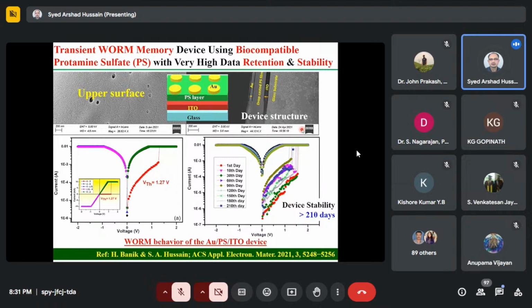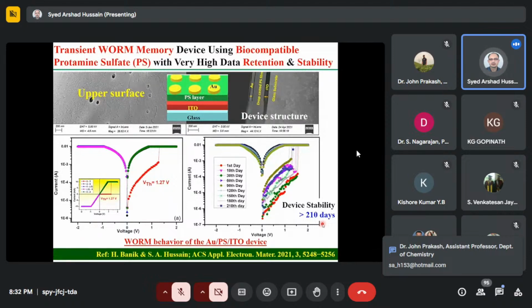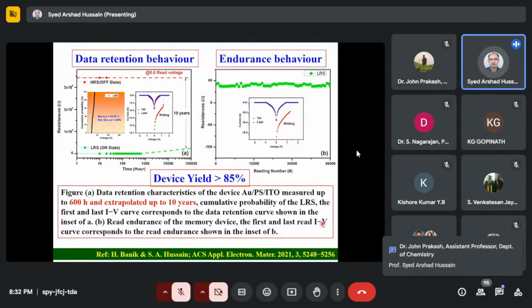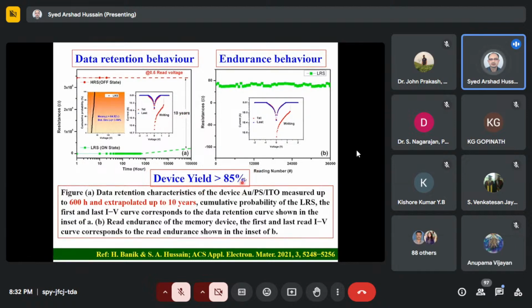Then we designed memory devices using Protamine Sulfate. This is another protein, and we have again demonstrated the write once, read many applications using this protamine, and we have seen that the device is stable even more than 200 days. We studied, but you see, after a few hundred days, it's difficult to go on doing experiments because our scholars, students, they need publications for their PhD. So we have to stop and go for publications. But we try to extrapolate and have some idea about the stability also. So here we have seen that the device is stable even after 10 years. You can see that we applied the extrapolation method, and the device yield was greater than 85%. This is very good in terms of applications also.